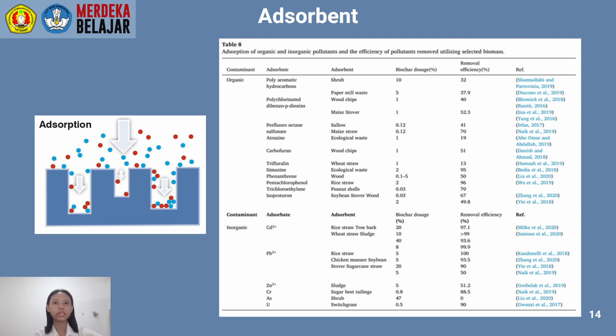Contaminant: organic; adsorbate: polyaromatic hydrocarbons; adsorbent: shrub; biochar dosage 10%, removal efficiency 32%. Polychlorinated dibenzo-p-dioxins; paper mill waste, wood chips; biochar dosage 5 and 1%; removal efficiency 37.9 and 40%, and so on. And contaminant: inorganic,